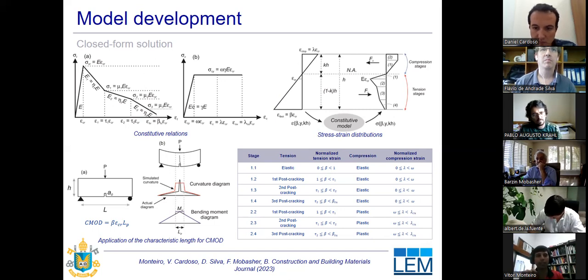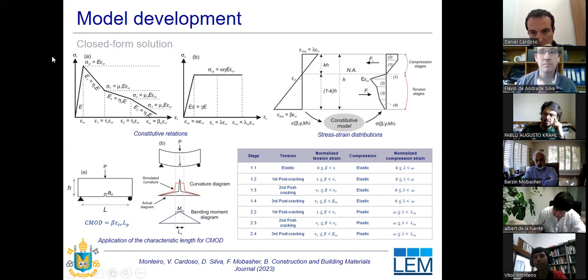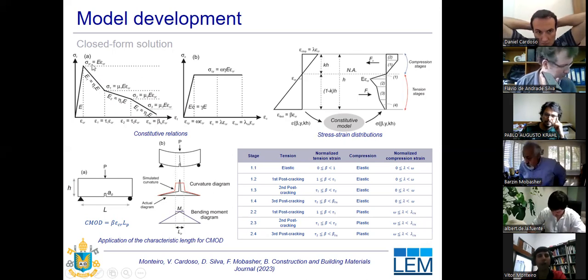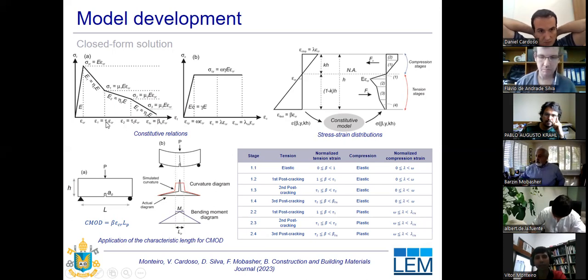So the models need to have a good application of the constitutive relations. So for compression of the FRC, we use an elastic plastic behavior. And for tension, we use a quad linear model, which has four lines representing the pre-peak and the post-peak behavior of the FRC in tension. It's possible to verify that the post-peak is majorly analyzed in terms of adimensional parameters, which are all calculated as a function of the cracking strain and stress. So the post-crack stresses are calculated as a function of the cracking stress. The same thing is done for the strains.